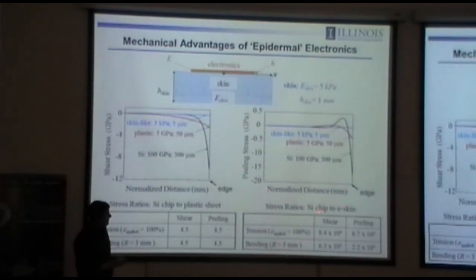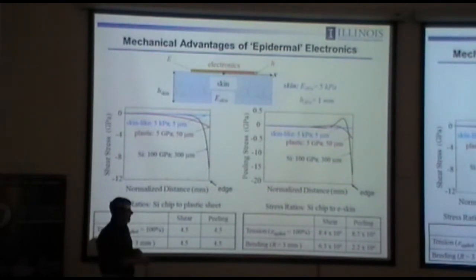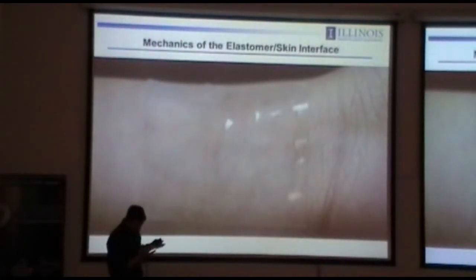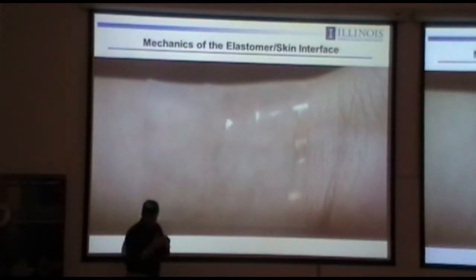But now if you consider silicon chip compared to electronic skin, the skin-like geometry, look at the same ratios, almost 5 orders of magnitude. So now that has a dramatic effect on the way you think about materials that can engineer strong adhesion between the device and the skin. And in fact, with the very tiny interface stresses that develop when you have an electronic skin type mechanics and thicknesses are so low that van der Waals forces can keep the device on the skin without any adhesives or straps or penetrating pins or tapes at all. And that's an important outcome and really drives the design around low modulus and small thickness.